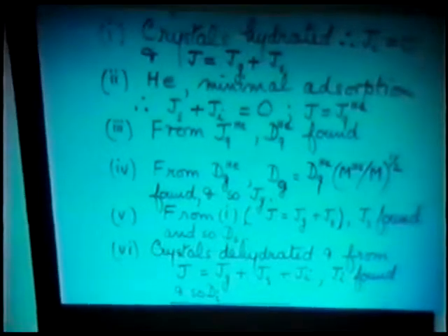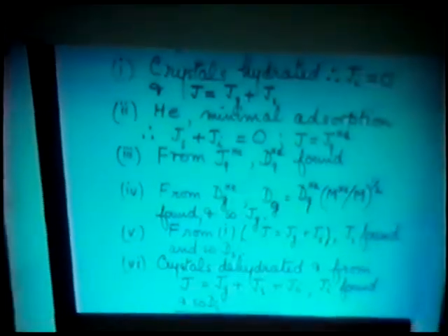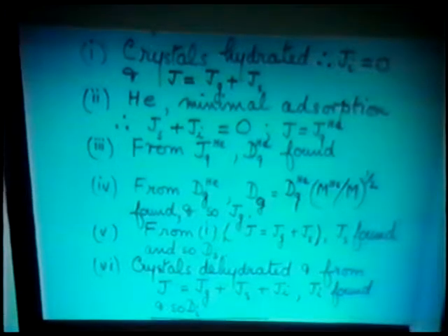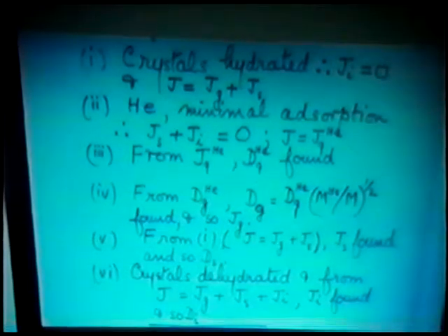Now, because particularly of the presence of the graphite, you have to take into account three components of flow. JS, the component of flow called into play by the presence of mobile adsorbed films in a concentration gradient, can now probably not be neglected. At least we didn't find that we could neglect it.